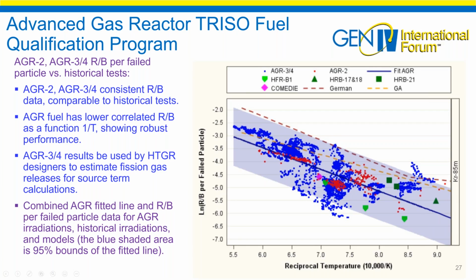tests are here, the GA tests, AGR-2, you'll see, wow, we have a lot of data here. AGR-3/4, well, yes, we had a lot of designed-to-fail particles, so okay, we had a lot of temperatures and data. What does this mean? Our data is consistent with what we have seen in historical tests. The AGR fuel has a lower correlated release to birth as a function of inverse temperature. So it is very, very robust. That's this average line here that was statistically checked and correlated.